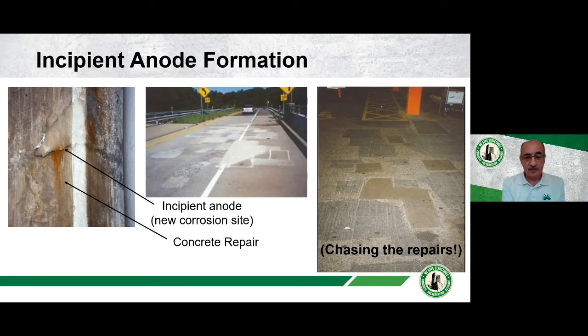Fosroc came to us with a real problem that they had, which was when they were selling repair materials, the complaint that was coming back was that there was corrosion occurring around the periphery of the repair. And they asked us to investigate this and see if we could come up with a solution to the problem. And as you can see here, this is an original repair, but within 2 or 3 years, it started having corrosion just on the edge of the repair.